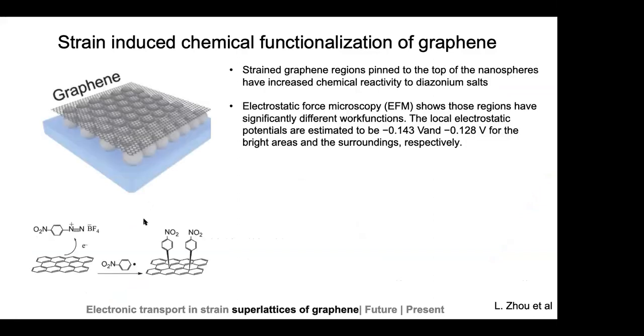For example, in the structure which you saw right now, graphene was transferred onto a close-packed structure of silicon dioxide nanospheres. And what happened as a result is that the graphene, which is in touch with the top of each of the nanospheres, has greater strain, and the strained graphene, it was observed, has greater reactivity to diazonium salts.